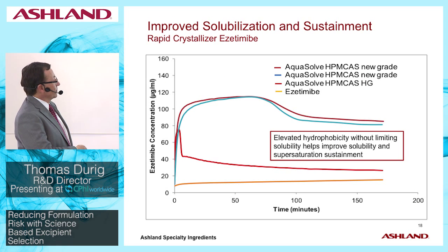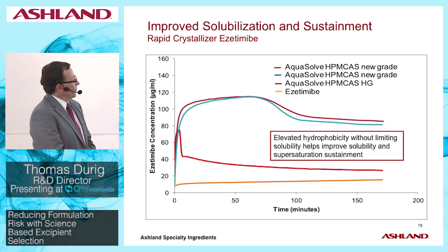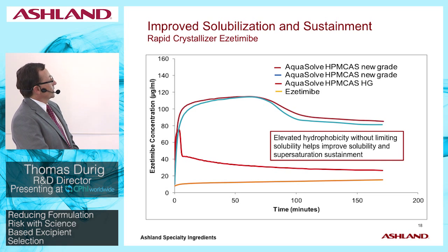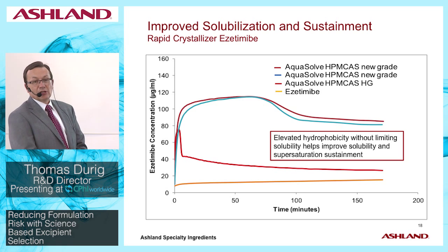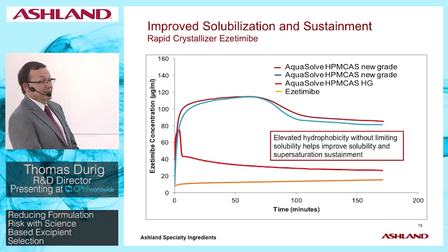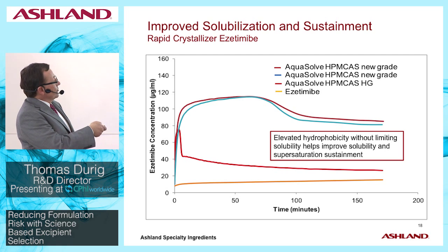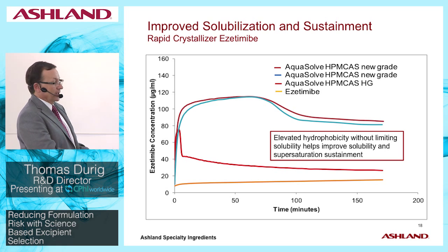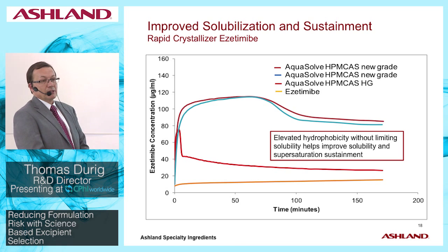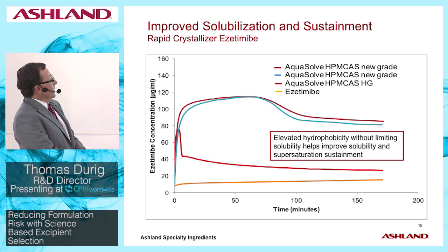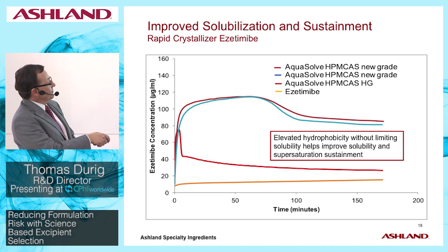And by way of example, here we have an example of solubilization of a model drug, which is ezetimibe, which is used here as a non-proprietary model of a rapidly recrystallizing, rapidly precipitating drug. And as you can see, with our new HPMCAS analogs over native ezetimibe, we're achieving something like a 7-fold increase in solubility, nonetheless at a 60% drug load. And we also are achieving a significant improvement over our current HPMCAS, which shows a very rapid precipitation after initial solubilization.